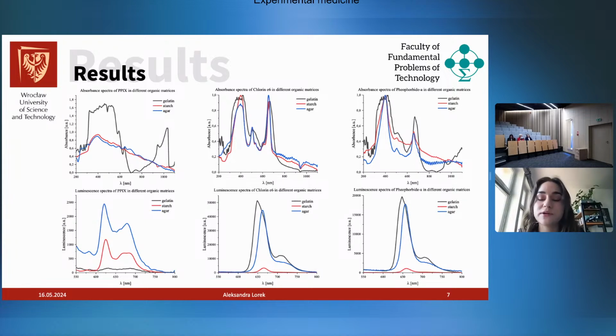Here are 6 plots that represent data from measurements for 3 biopolymers and selected photosensitizers. And based on them, quantum efficiency can be measured. As you see, for protoporphyrin IX, gelatin matrices had much bigger absorbance than starch and agar. And despite that, luminescence is the lowest.